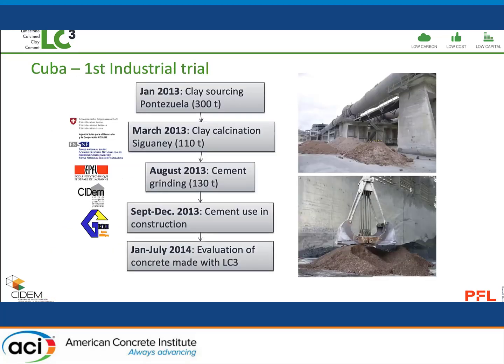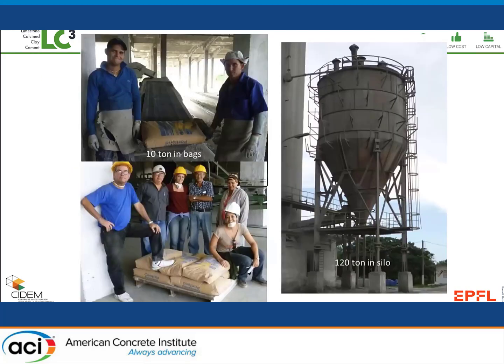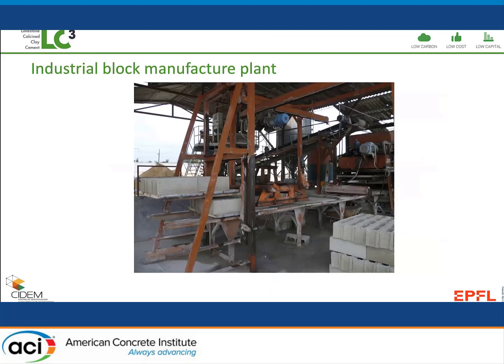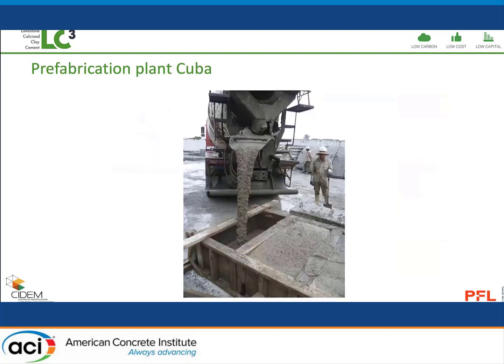So this was the first production of calcined clay we made in 2013 in Cuba. Just to emphasize the point, this was by no means a sophisticated operation. This was quite an old kiln, and yet they could successfully calcine the clay. They could grind it and put it into bags. They could take it to the local block making plant, give it to the operatives with absolutely no additional training. They could use it on a one-to-one replacement basis, and the product had absolutely good strength for the application.